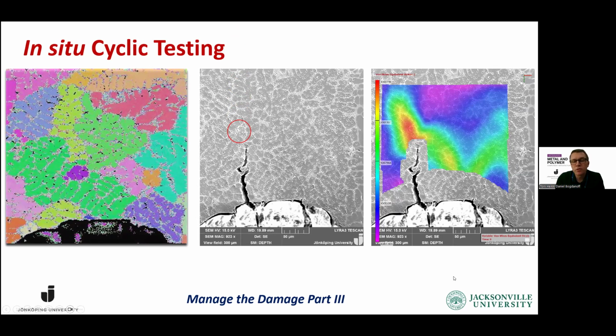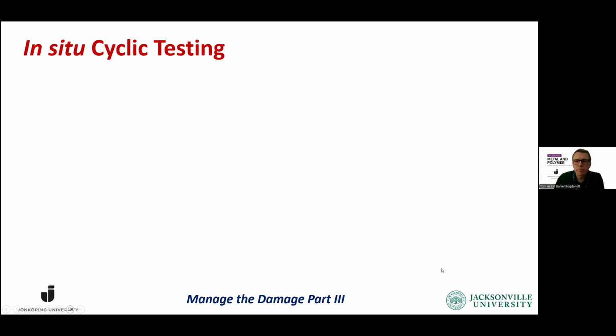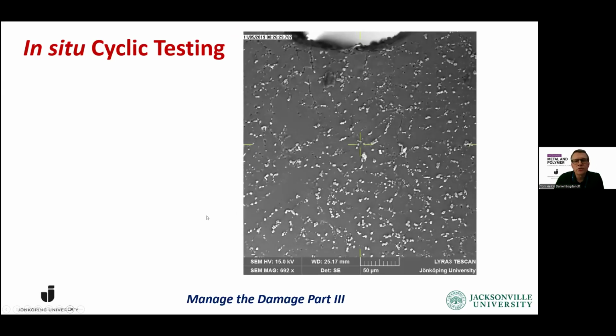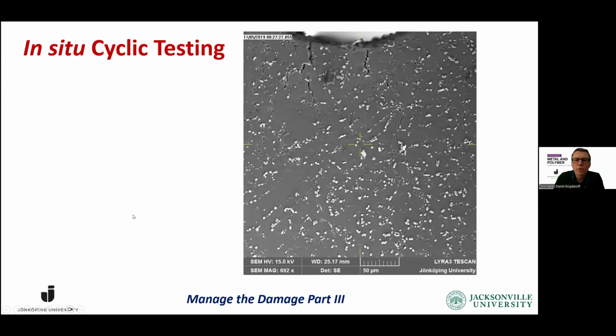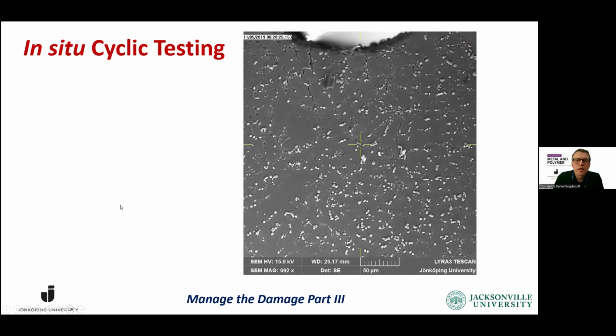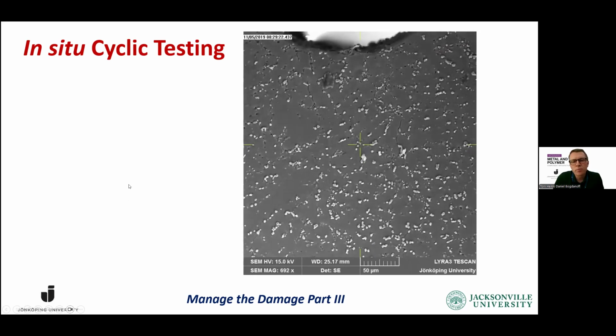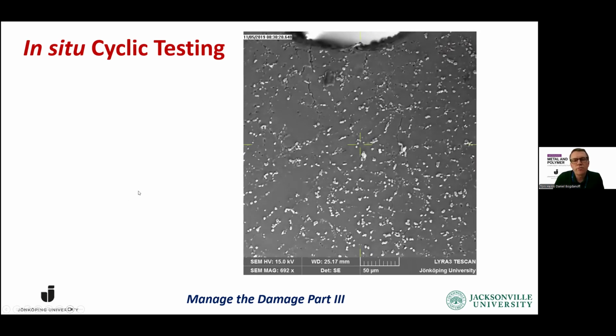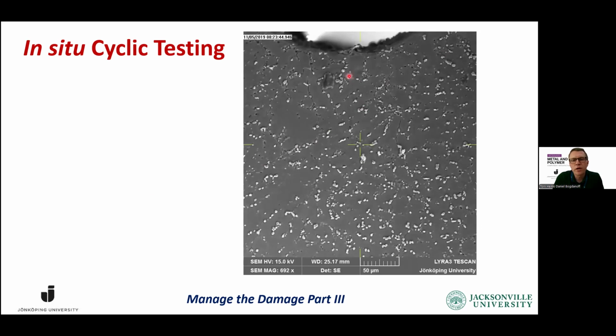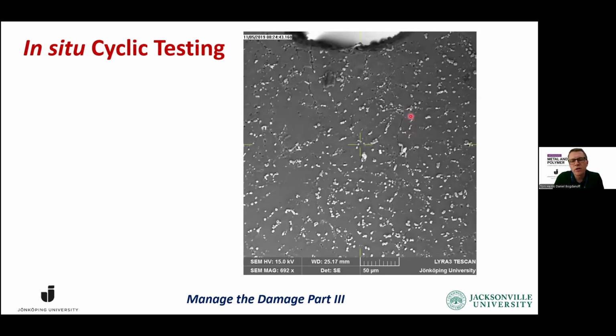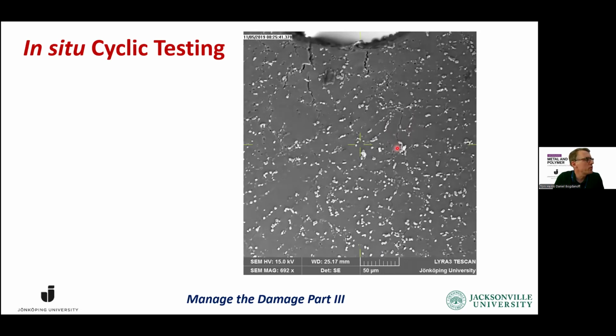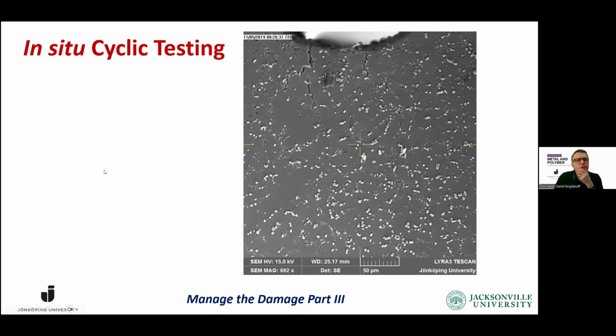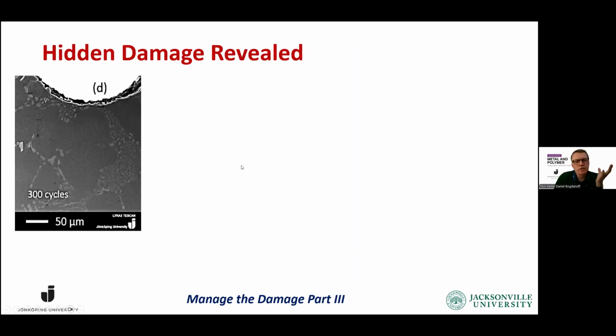We can actually see that we have a strain concentration where something is happening before. But one of the best advantages is that we can follow it live while the test is running. So here we can see the crack propagation forming during the test. And what we see is that we have crack propagation to the top left, but we also have a secondary crack appearing in the center, and a lot more cracks in front of the propagating crack. So if we continue, we did this on different material.